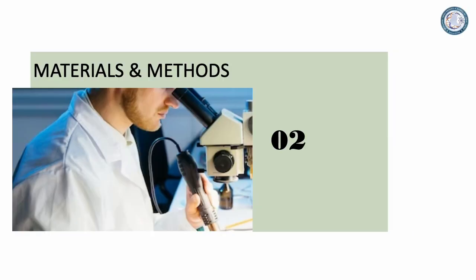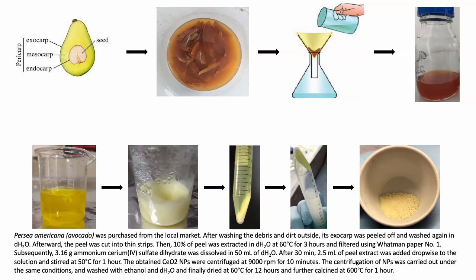Okay, let's see the methods. Persea americana avocado was purchased from the local market. After washing the debris and dirt outside, its exocarp was peeled off and washed again in distilled water. Afterward, the peel was cut into thin strips. Then 10% of peel was extracted in distilled water at 60 degrees Celsius for 3 hours and filtered using Whatman